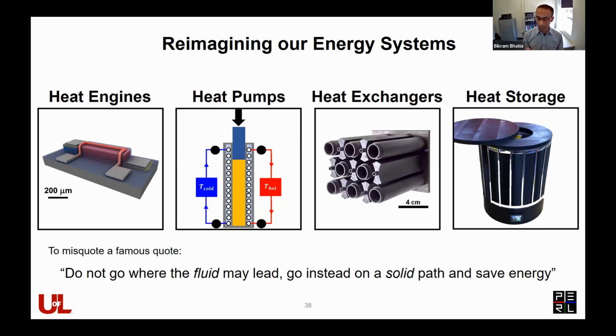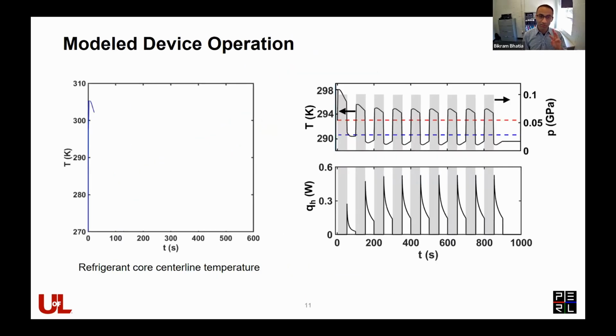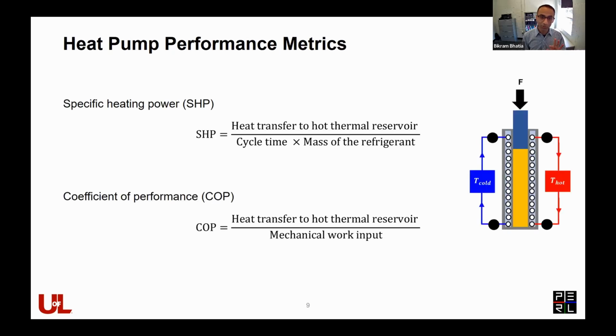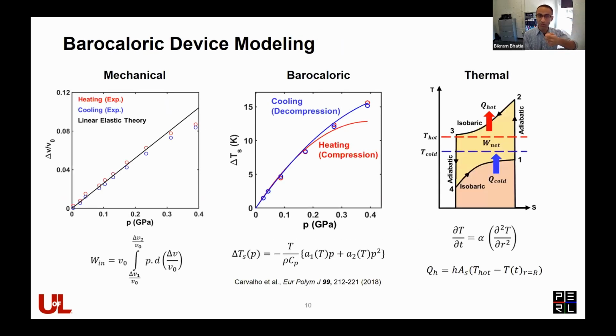Right. So if I go back to maybe the model that I showed, there are essentially three parts that you have to think about, right? There's a force, there's a barocaloric response, and there's a thermal transport. So if you have a stack maybe interdigitated with some high thermal conductivity media, that definitely helps the thermal transport. You have to ensure that the pressure gets transmitted uniformly, which is a challenge in some solid media because the Poisson's ratio is not 0.5, so they're not always very compressible, so the pressure doesn't get transmitted.